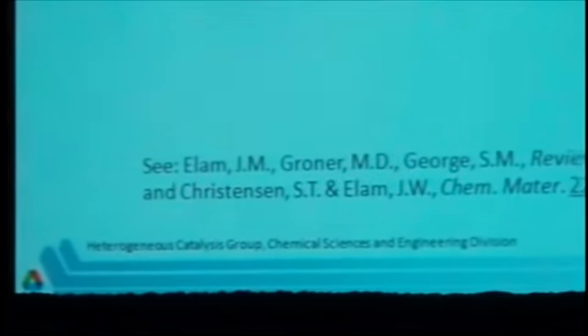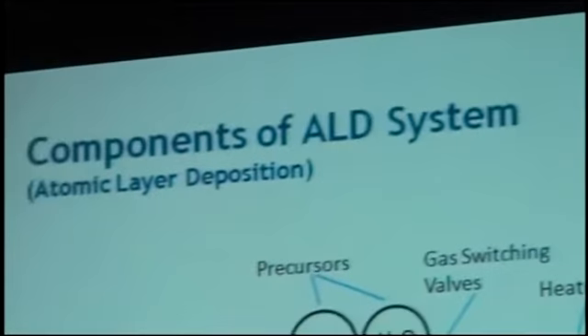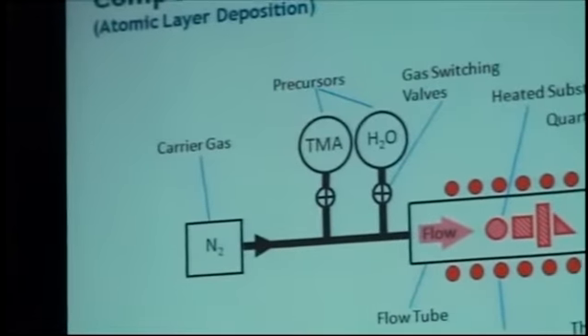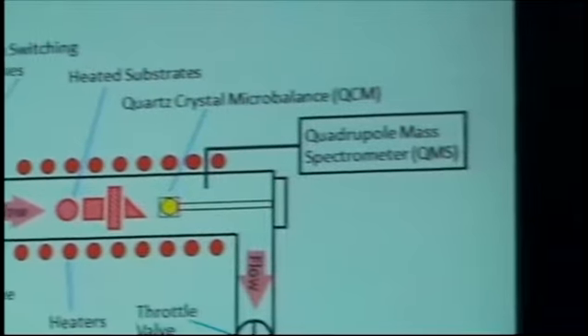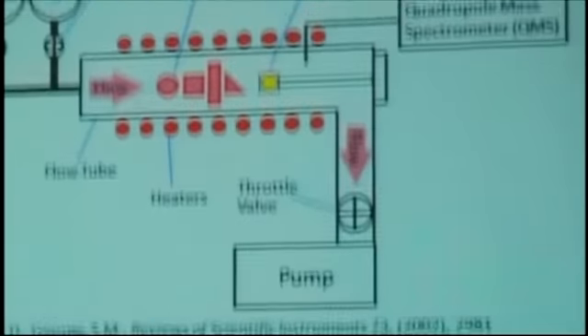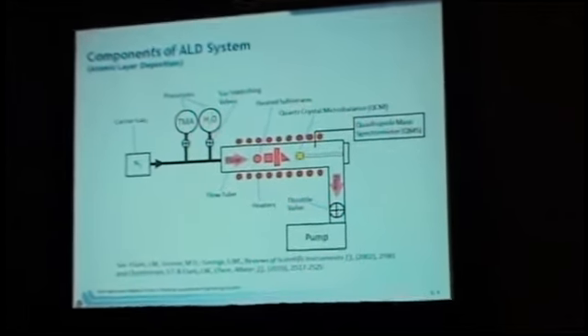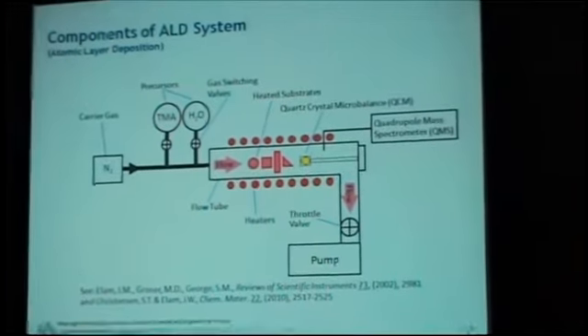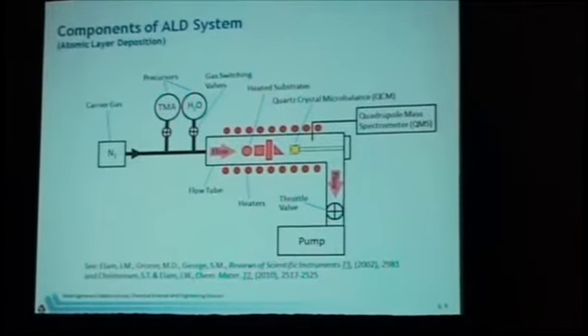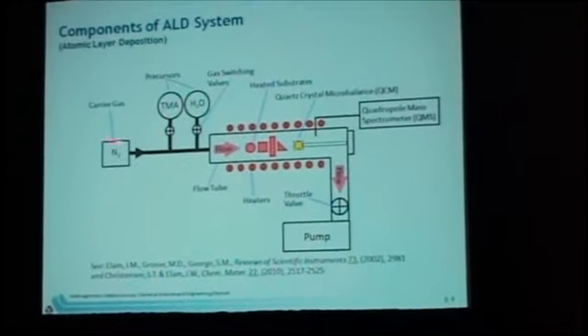Atomic layer, some of the catalysts, the original concept was to make catalyst that we prepared with atomic layer deposition. The ideal is to have a nice smooth catalyst, everything well formed, and to put promoters on in the same sort of way. Now ALD is not an inexpensive way to do catalyst preps, but we were giving it a shot to see if we could get a better catalyst that was a major change. And as a summary, it wasn't.